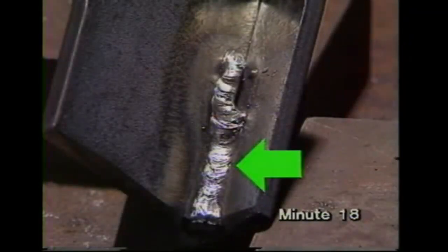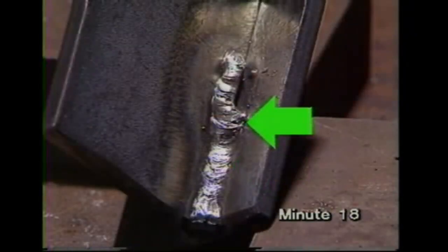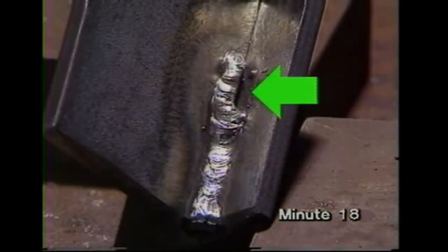If you move along the joint too slowly, then the weld metal piles up, trapping slag underneath. Normal speed. That's where Max slowed down, and here the slag prevents correct fusion, as we can see from the macro section.